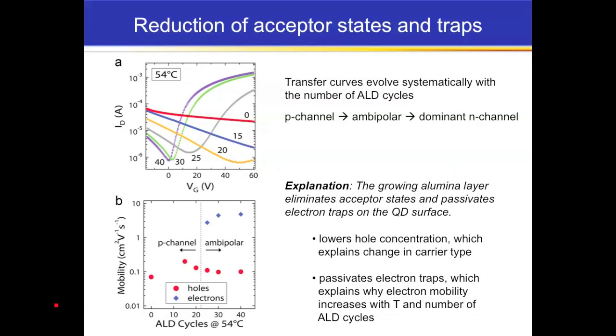So we were able to get some insight as to what's happening with this process by just looking at the field effect transistor transfer curves as a function of the number of ALD cycles. So this is 0 cycles out to 40 cycles. And what we can see is that at first the material is a very heavy p-type conductor, which we can't really modulate very well with the applied gate field. That indicates that it has a high carrier density.